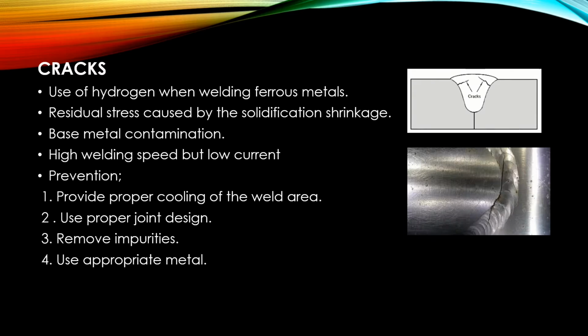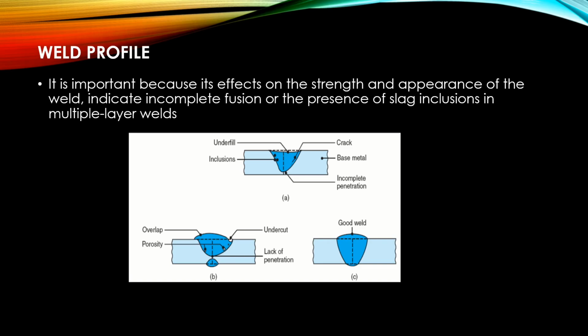And for the cracks, causes are use of hydrogen while welding ferrous metals, residual stress caused by solidification shrinkage, base metal contamination, and high welding speed but low current. To prevent these cracks in welding, provide proper cooling of the weld area, use proper joint design, remove impurities, and use appropriate metal. And for the last, weld profile. Weld profile is important because it affects the strength and appearance of the weld, and can indicate incomplete fusion or the presence of slag inclusions in multiple layer welds.